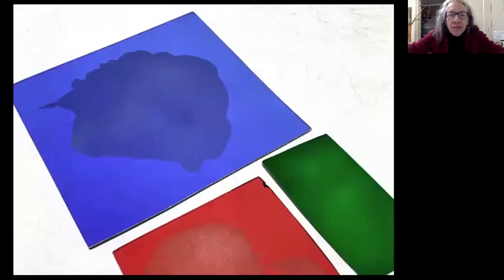What I want to show you are the very slightly cloudy areas, like right in there and there, and it's hard to see, but there and there. The thickness of the flash will be different on every piece of glass. Typically, the darker the color, the thicker the flash, although that is not always the case. The flash layer on blues and greens and pinks can be relatively thick, and on reds, it can be relatively thin. When you sandblast, therefore, you may want to go a little further with the blues and the greens than the reds. If the flash layer is thick, you will definitely want to sandblast a little more, hence these clouds. That green piece, that is really thick.